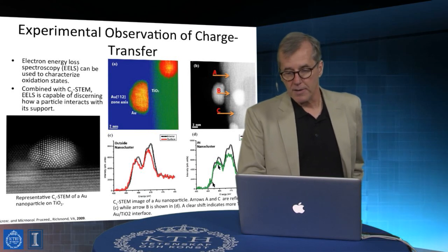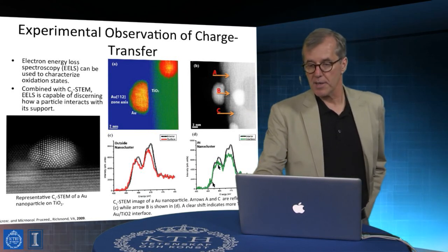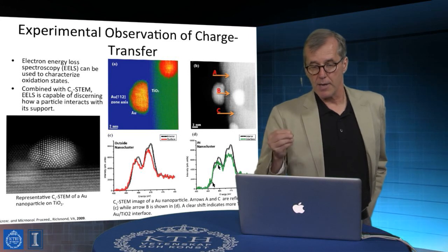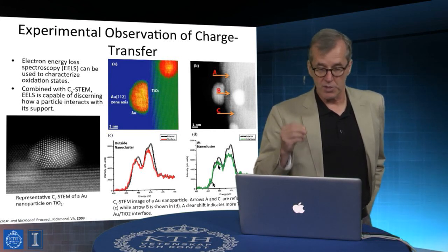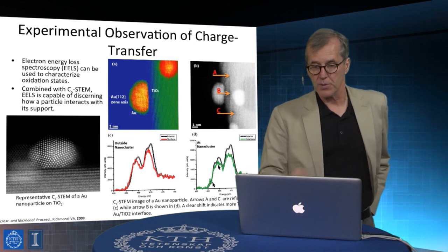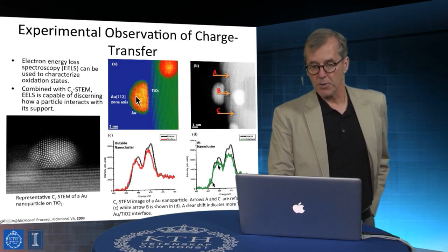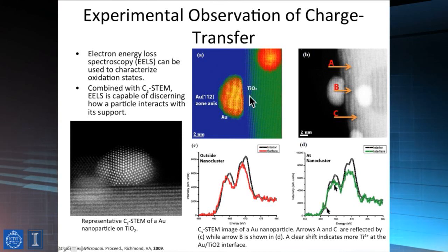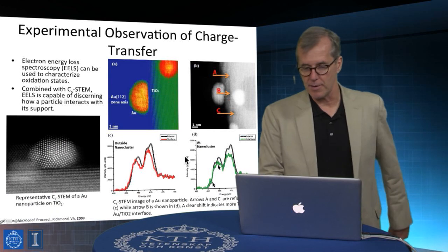Okay, and finally, I'll note one last thing, that with very fine probe beams and high energy resolution, which is another aspect that comes into play with this class of matter, we can also look at, in this particular case, gold clusters supported on TiO2. For those of you who study catalysis, this is a very interesting catalyst where gold becomes active when it's really small, but on an active support. And the properties are related to charge exchange characteristics associated with the metal support interactions. It's my theory. It's not agreed upon in the literature.